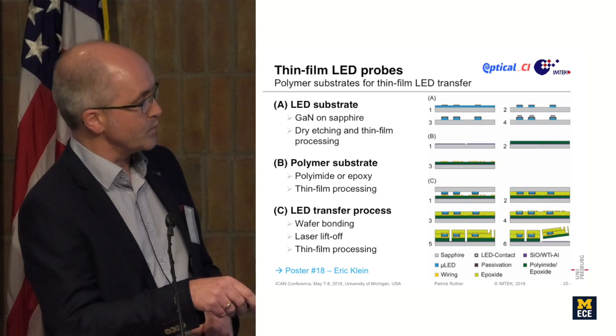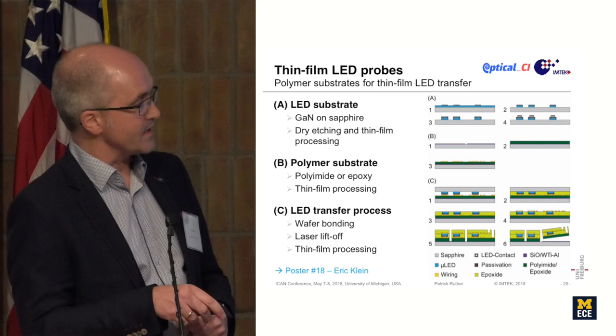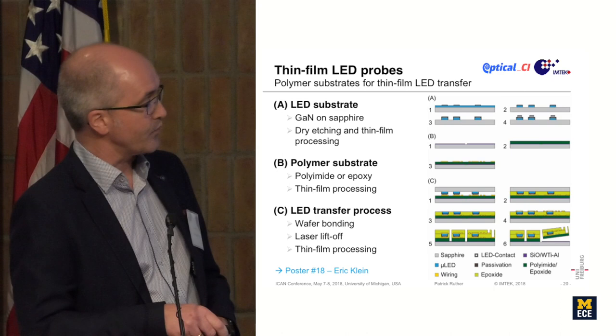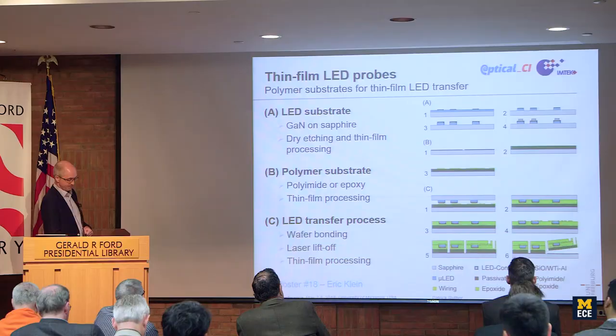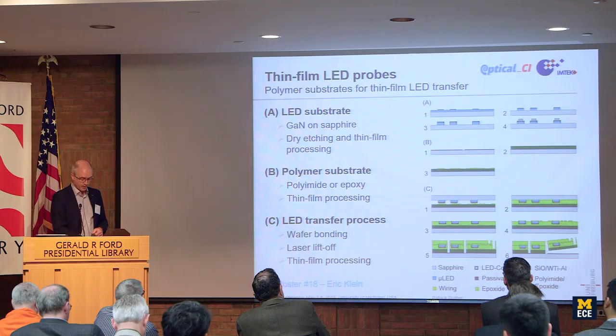We do then an underfill to mechanically secure everything. The sapphire is then lifted, in this case, by laser liftoff. We do the metallization on top and insulation, and we pattern the entire probe so that we can lift that off.